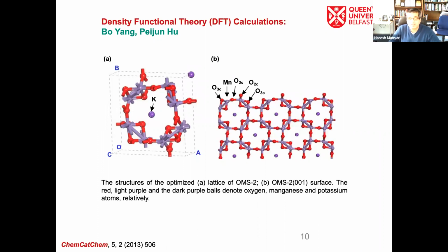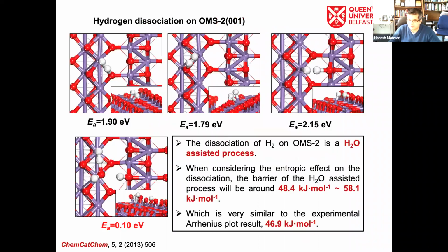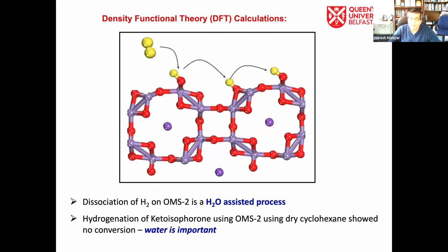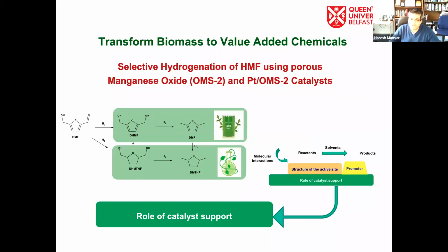And we did, with our colleague Professor Peijun Hu, a lot of DFT calculations to look at the adsorption of the molecules on the surface. And we also looked at the mechanism behind this. The mechanism was water-assisted dissociation of hydrogen. Direct dissociation was much more energy demanding, but the activation energy barriers were much lower in the case of the water-assisted process. So the dissociation of hydrogen on the surface is the water-assisted process, and the selectivity to the product is a function of the adsorption on the surface of the material.